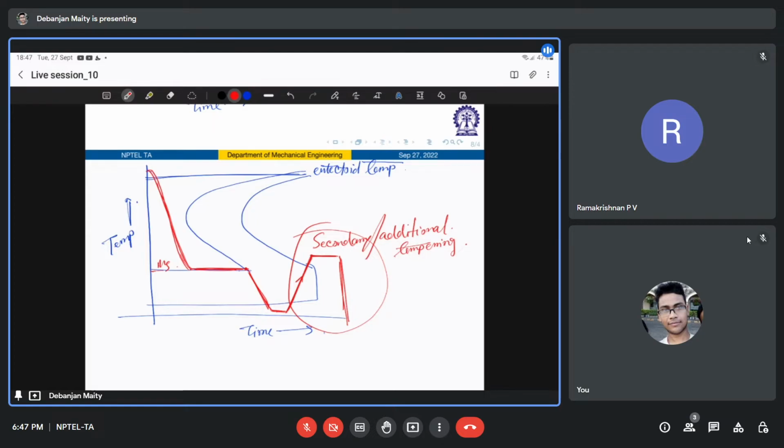So you're quenching from the austenitizing temperature into maybe a hot fluid medium at a temperature above the martensite start temperature, and then the cooling is stopped just above that martensite transformation region to allow sufficient time for the entire component to reach that same temperature, and then again you continue cooling at a moderate rate, maybe through that martensite region. Moderate rate in the sense it can be air cooling, right? And then it is followed by some usual tempering process to impart toughness and better ductility.